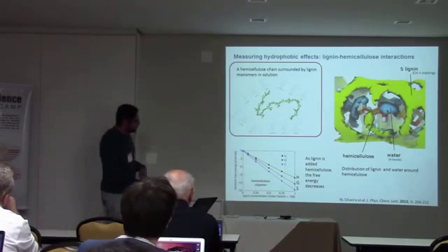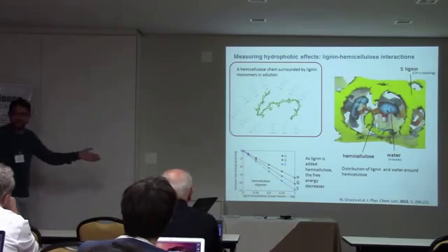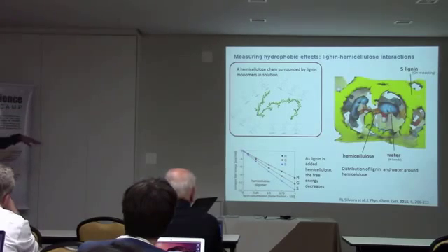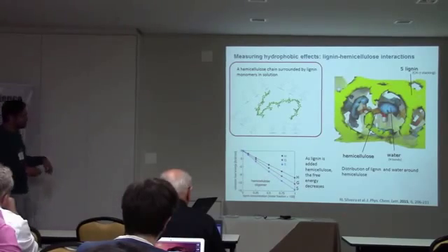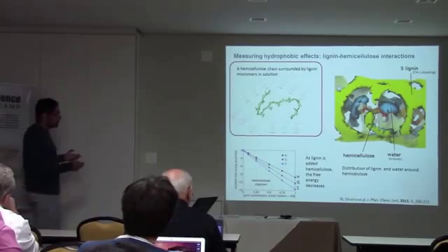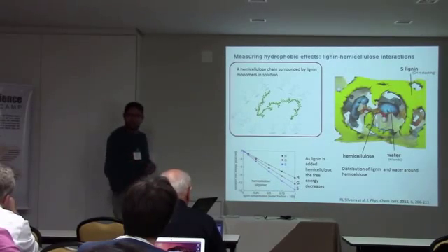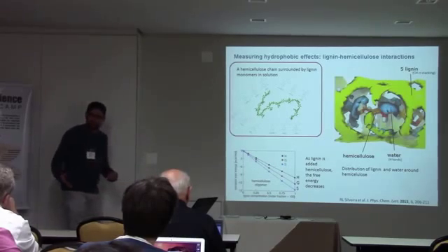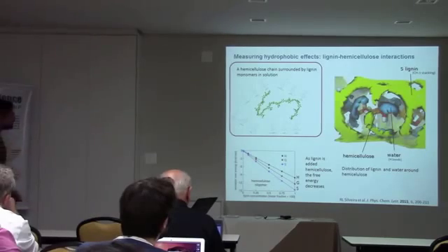this profile here. So this is also, to have this experiment sometimes, some genetic modification that increases the S lignin and reduces the H lignin or G lignin actually results in stronger cell walls, so they need more intense pre-treatments to break down the cell wall. And the opposite is true in some cases too. So that's why.